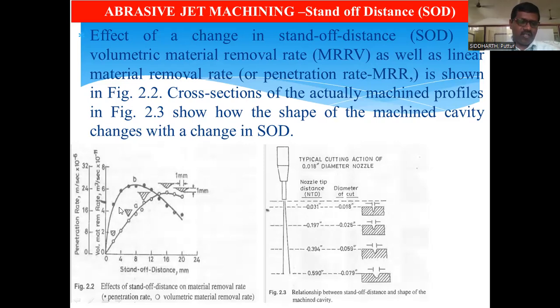And for the penetration rate also, when the standoff distance is less, the penetration rate is very low at point 0. Then when you increase the standoff distance, the penetration rate also increases. At 8 mm, the penetration rate is very high. If you still increase the standoff distance, the capacity or velocity of the abrasive particles is reduced, so the penetration rate also comes down.